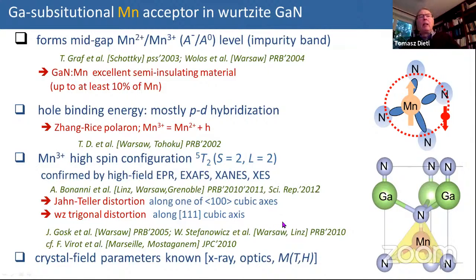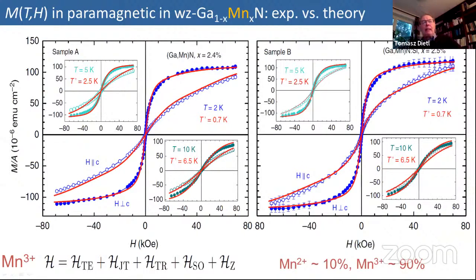And you have here an example of magnetization as a function of magnetic field at low temperature. Here it's a 2% sample, and you can see the description of magnetization. You see that the easy axis is in plane, perpendicular to the c-axis, and the hard axis is parallel to the c-axis. And this we can, of course, describe theoretically very nicely, taking into account the tetrahedral field, Jahn-Teller effect, trigonal distortion, spin orbit, Zeeman splitting, and so on. It's a kind of standard approach to magnetization in dilute magnetic semiconductors.